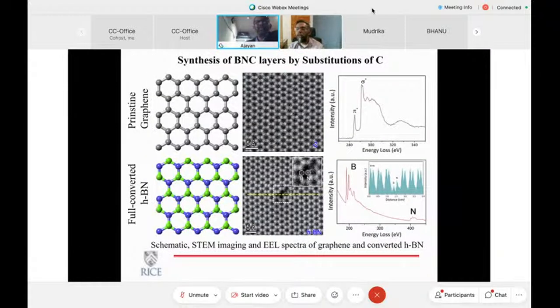People have looked at how exactly this transition occurs from carbon to BNC and then to BN, and many experiments have shown how this happened. If you look at hexagonal boron nitride and graphene, they are entirely isostructural. They have the same lattice parameter, same structure, but are poles apart. Graphene is a metal, and hexagonal boron nitride has a 6 eV band gap, which makes it a really good insulator. So these structures that I showed you, where domains of BN and graphene are stitched together, form a very heterogeneous electronic material, because some domains are electronically insulating and the other domains are very conducting in the plane.